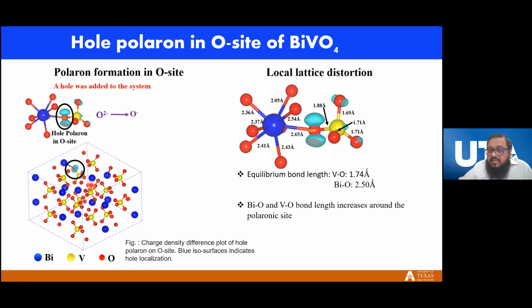It's my understanding, and I worked with John Turner at the National Lab as a postdoc, and you can find his seminal work in photo-electrochemical water splitting. So my understanding, and my work also shows, that electron and hole should have comparable mobility. Exactly, because the minority carrier has to move, otherwise I cannot get the second half of the reaction. Thank you very much. I think we should propose for the others.